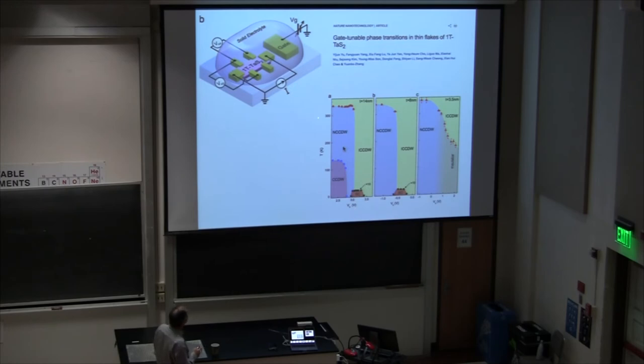It doesn't work the way the cartoon tells us it's supposed to work. Here's some work coming out of China and Rutgers. This material, tantalum disulfide, undergoes a complicated series of charge density wave transitions. You can tune the phase diagram with gate voltage. There's even a superconducting dome here. It's really beautiful work. All this ionic liquid gating works, it just doesn't work the way the cartoon says it works.